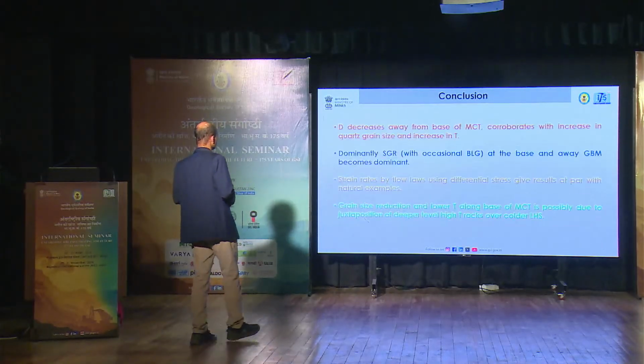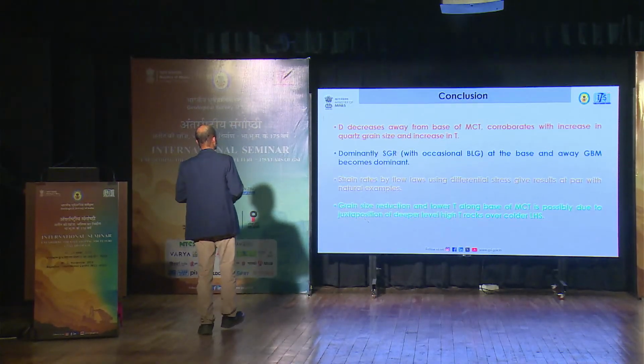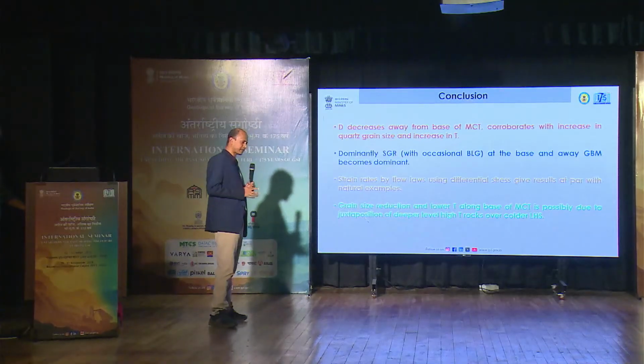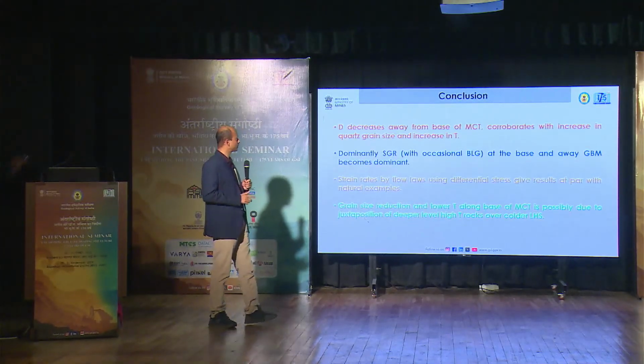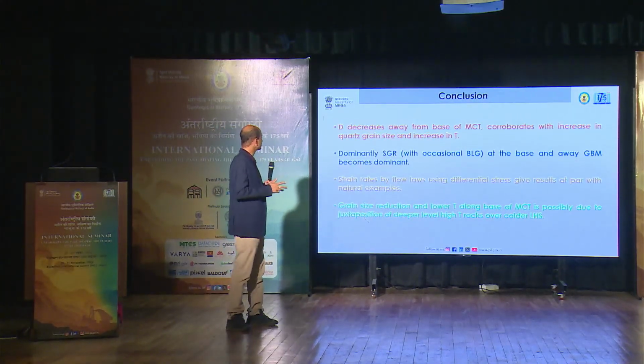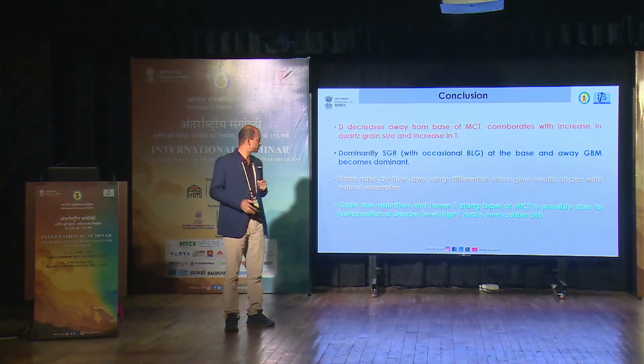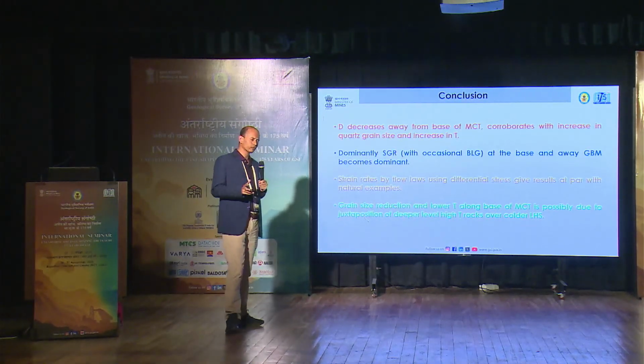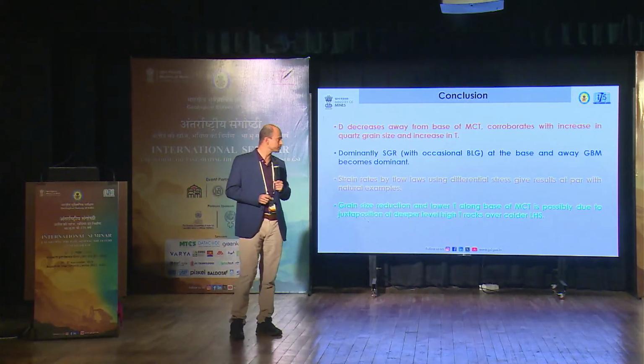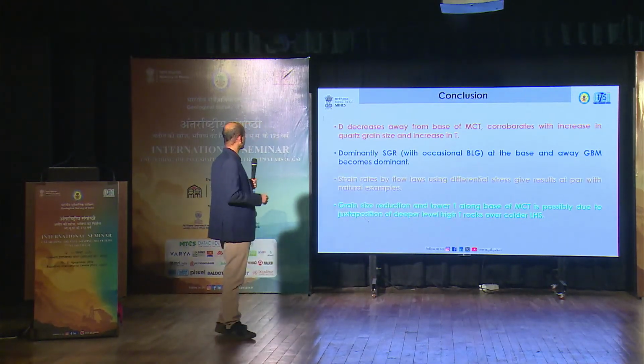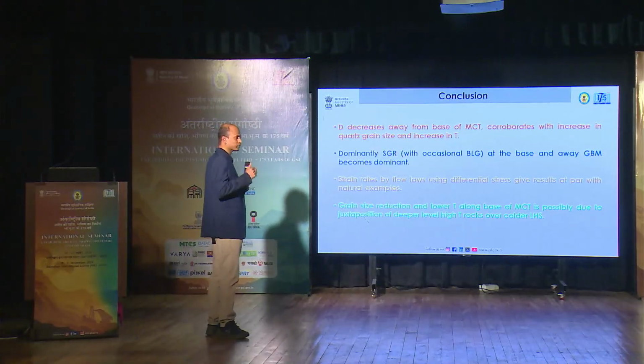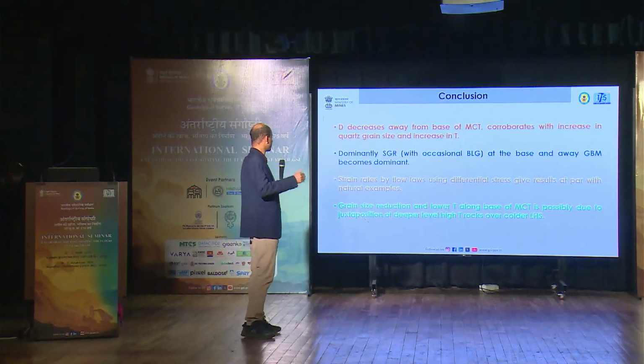Next. So to conclude, we see that the area perimeter based fractal dimension decreases away from the base of the MCT, which corroborates with the increase in quartz grain size and an increase in temperature. Further, we started off with subgrain rotation with occasional bulging recrystallization at the base, and now we get dominantly GBM as we go away from the base of the MCT.